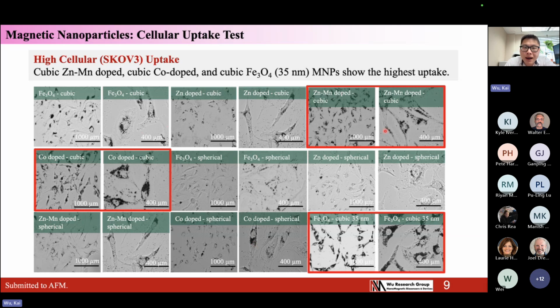I also want to highlight 3 particles. As you can see, I highlighted them: the zinc manganese doped cubic particle, the cobalt doped cubic particle, as well as the 35 nanometer Fe3O4 cubic particles. They show much higher cellular uptake of the nanoparticles, which tells you that if we want to choose particles for imaging purposes or hyperthermia treatment of tumors, we want particles to be internalized by the cells. So the better choice will be these 3 particles. They will increase the amount of particles that internalize in the cell and create a higher signal or better performance in hyperthermia treatment.